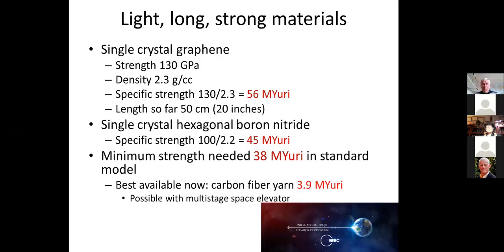So, light, long, strong materials: single crystal graphene with a tensile strength of 130 gigapascal and a density of 2.3 times water. We need the specific strength because it's got to be light and strong. If you divide the strength by the mass density, you get that number, 56, in MYuri, which is a unit we've invented for space elevators because the other units don't apply very well to space elevators. The biggest piece that's been made so far is 50 centimeters square, 20 inches square, but it's very, very promising. Single crystal hexagonal boron nitride is not quite so strong, but it's still good. It's better than we need, getting to 45 MYuri.